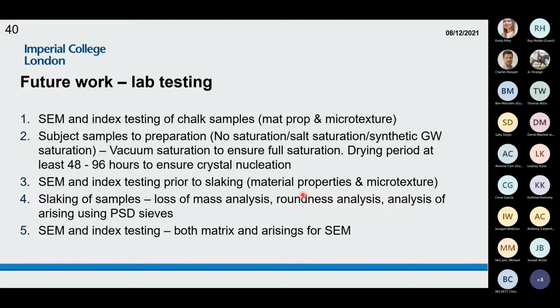The problem also is that you require vacuum saturation over quite a significant period because the rate of diffusion of the water into the chalk will take quite some time, and then the drying period to ensure crystal nucleation for weakening agents such as salt in there. Hopefully I'll undertake SEM and index testing prior to and after the slaking to see whether there's any difference between the two, and see whether the slaking process, rather than just being a mechanical process which removes material, actually changes the material properties of the samples in the slake durability machine.